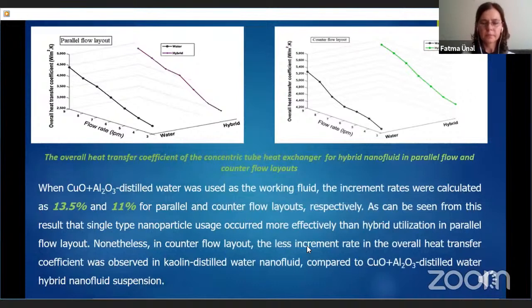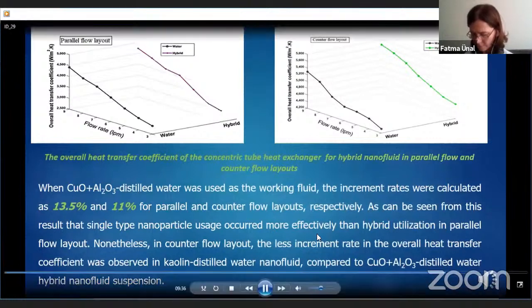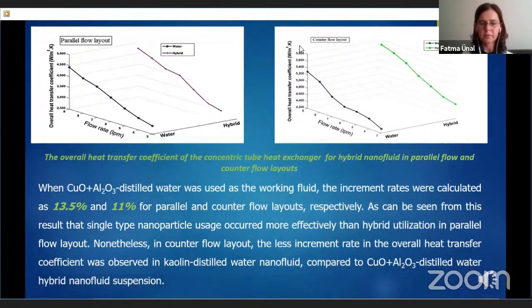As can be seen from these results, unitary type nanoparticle usage took place more effectively than hybrid utilization of nanoparticles in parallel flow layout. Nevertheless, in counterflow layout, the less increment rate in the overall heat transfer coefficient was observed in kaolin distilled water nanofluid compared to CuO+Al2O3-distilled water hybrid nanofluid suspension.